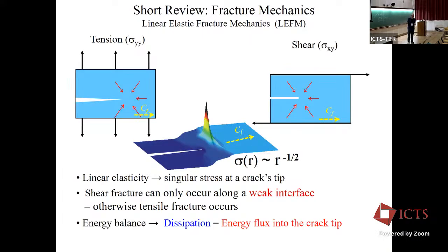One thing I haven't told you is that among the experts, shear fracture doesn't exist. So if I take a bulk material and I apply a shear, what the crack will do is rotate so as to be in tension at its tip. That's what the experts say. Personally, I'm not an expert, so I don't say that, but that's textbook. Textbooks are wrong in this case, but whatever.